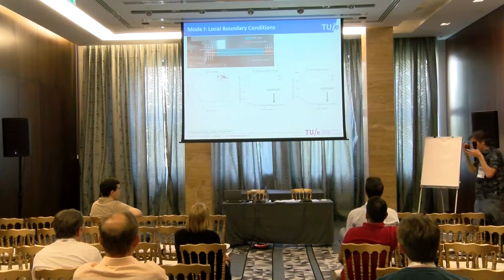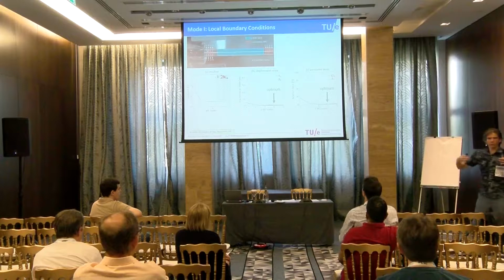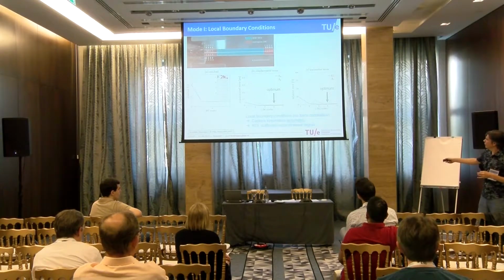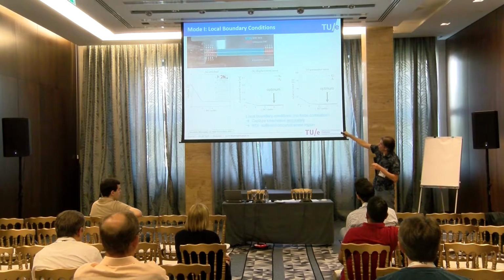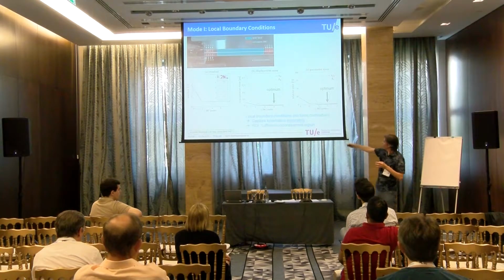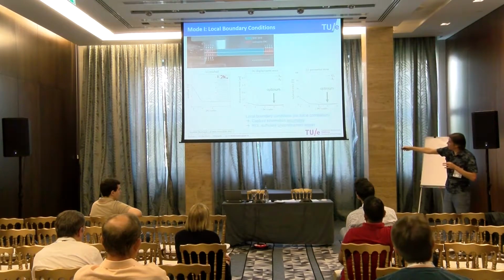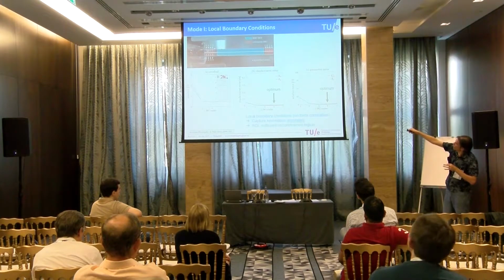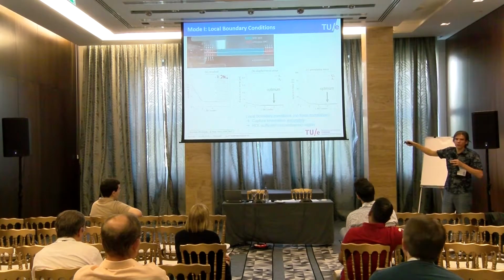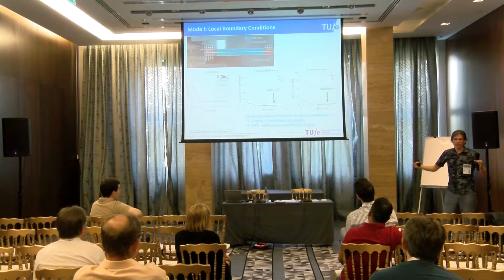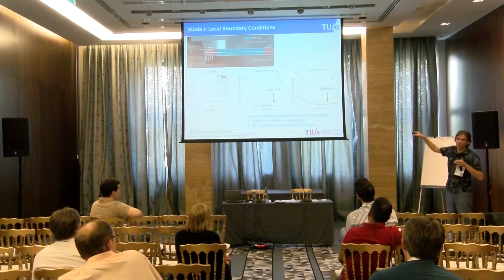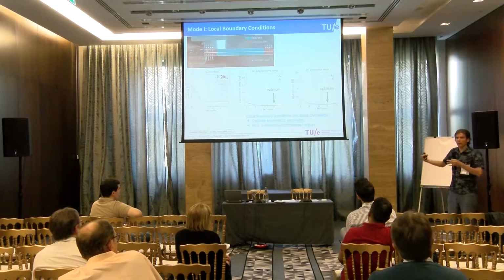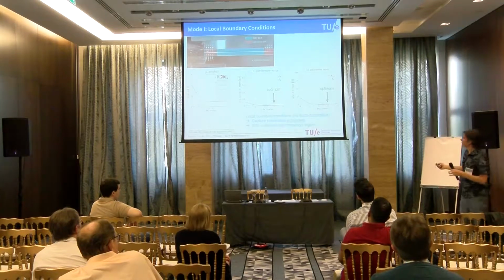So it's really about smart thinking of how much we need to prescribe at the boundaries. The local boundary conditions, when you don't have force, are really to capture the kinematics accurately, how what's actually going on, but we shouldn't do too much. We should have sufficiently unconstrained regions. If we constrain all these boundaries on the top and bottom side, then it goes wrong. On Monday, I showed that if you start including these boundaries as a degree of freedom, then you can have more boundaries.